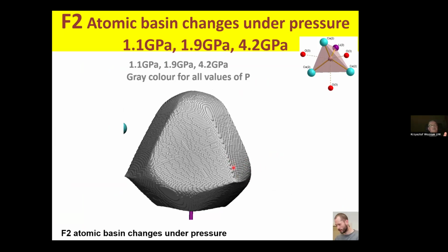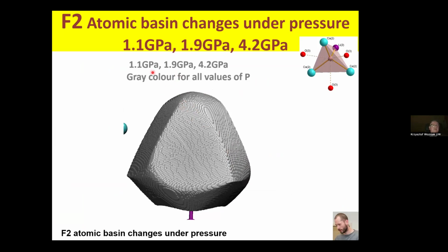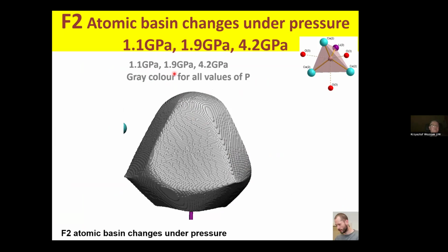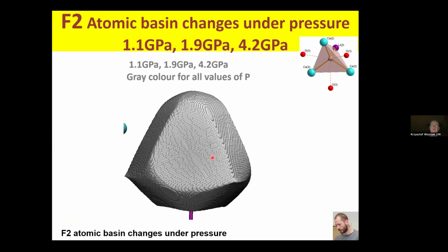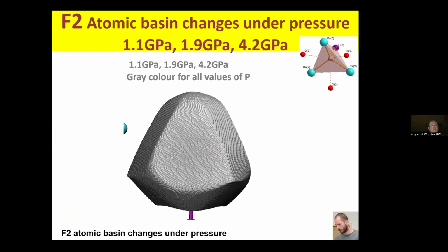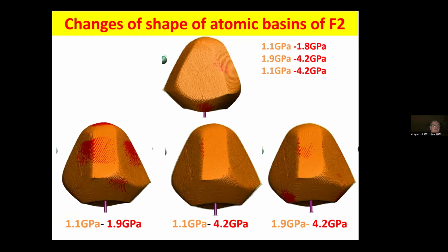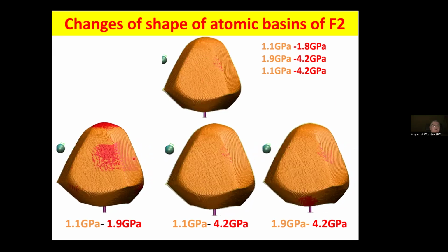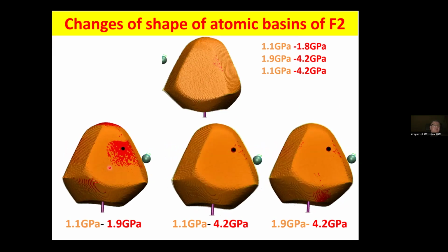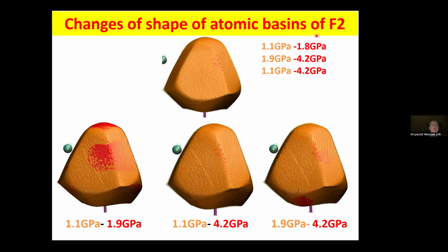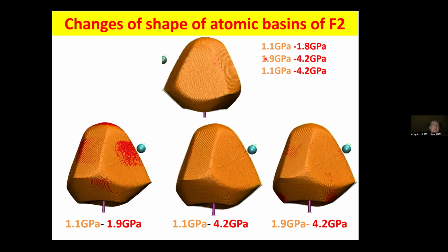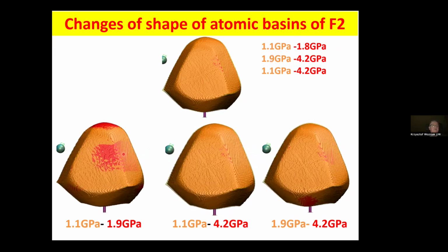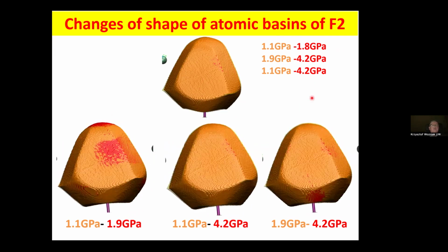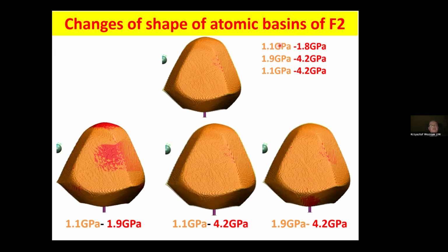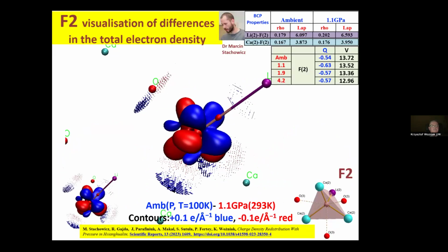Here, when you take a closer look, you can see small changes of this atomic basin, because these are three atomic basins obtained at 1.1 gigapascal, 1.9, and 4.2 gigapascals. So that's the scale of the changes. These are not big changes. However, we can easily measure them and quantify them. Here we have such projections of atomic basins obtained at higher pressures onto the atomic basins at lower pressures. So we can see how electron density is trying to escape from this atomic basin when we start pressing it and going to higher pressures.